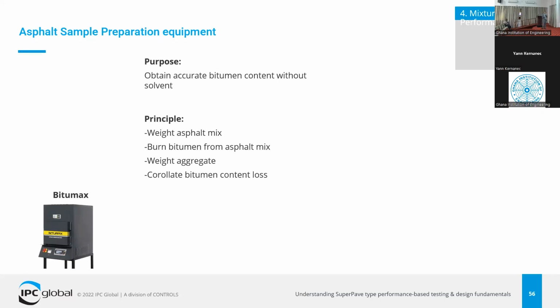You weigh your asphalt sample, you then put it into the oven, and the oven will burn the bitumen from the asphalt mix. So at the end, what you will have is your aggregate, and you weigh that aggregate at the end. And the difference between the original weight and the final weight is the bitumen content. The big advantage again is you do not have any solvent. It's a very quick process.